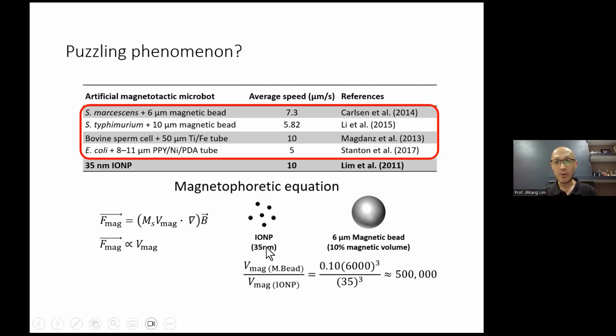So by right, we should witness speeds 500,000 times larger in this construct, and actually we didn't, right? It's very consistent. Everybody reports speeds of roughly 10 micrometers per second, which is on the scale of nanometer-sized particles. So this caught our attention, and we decided to pursue it and really try to answer these questions.